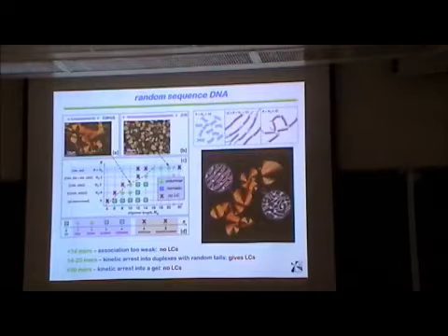So if the pairing overlap is less than, say, 7 or 8 base pairs, then they come apart right away. So in random 20-base DNA, overlaps that involve about 10 complementary bases have the highest product of probability times lifetime.